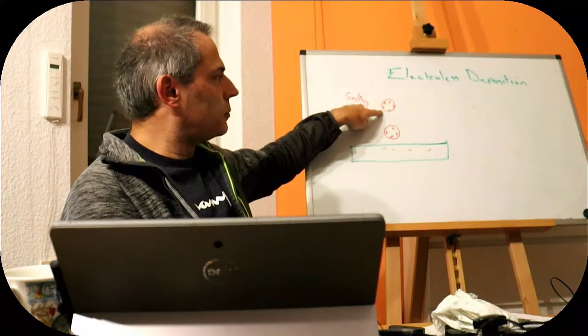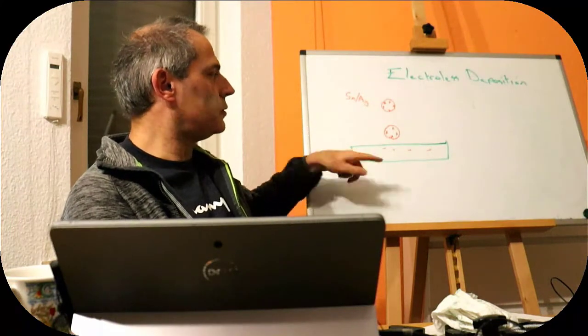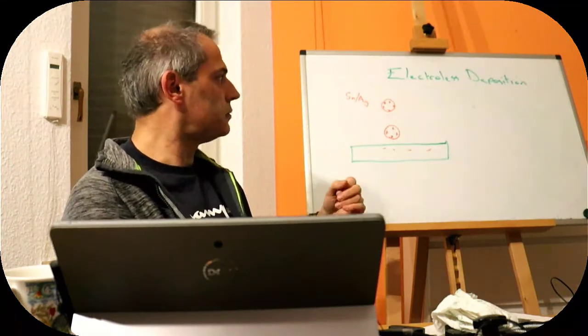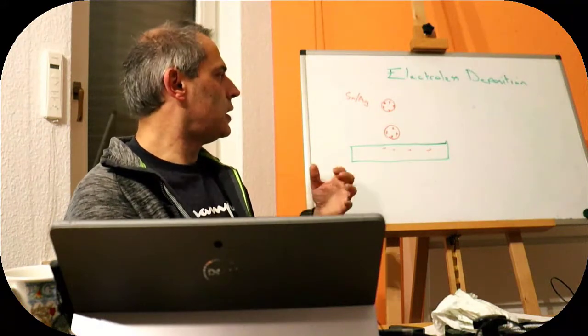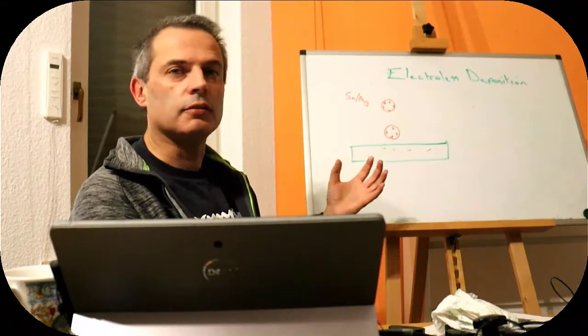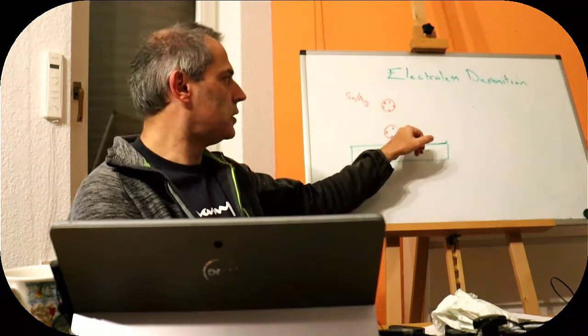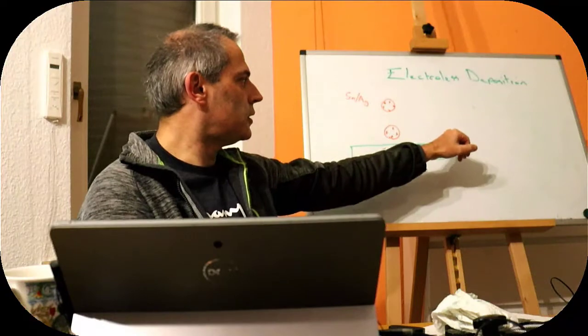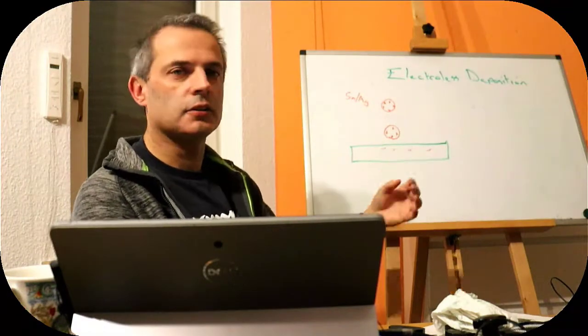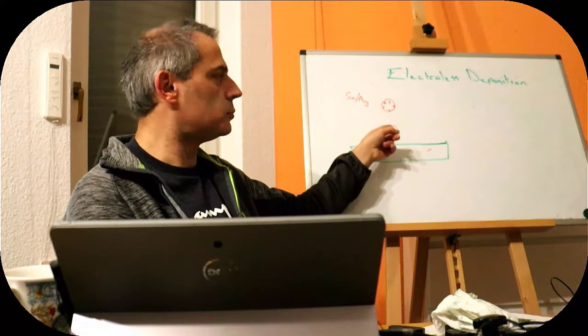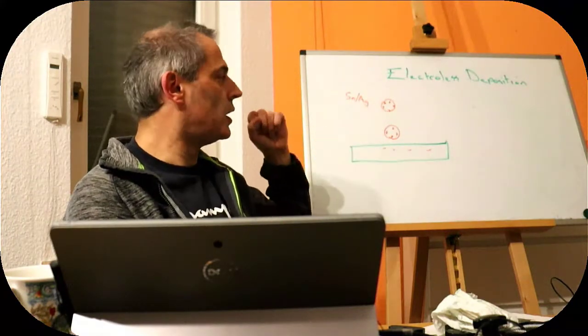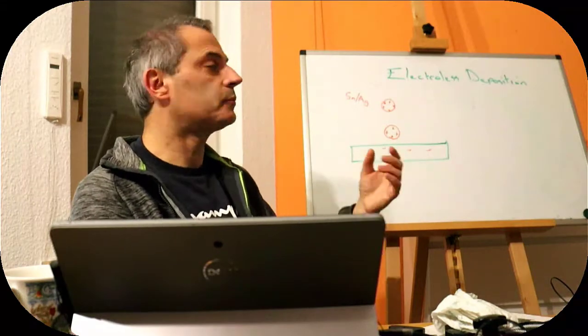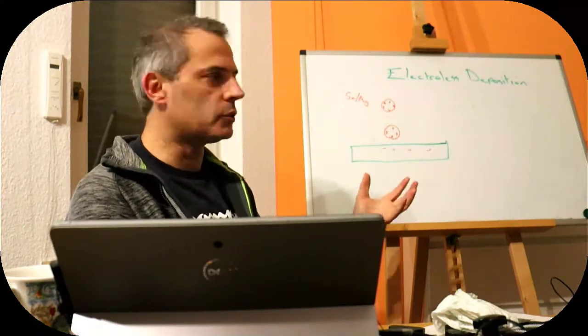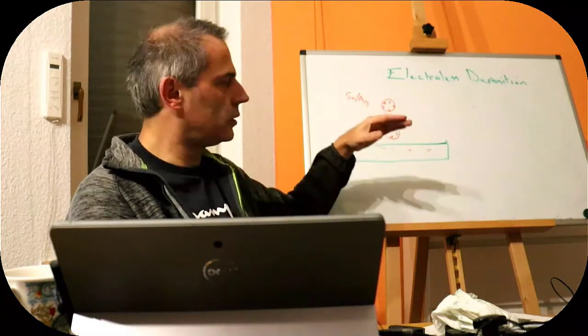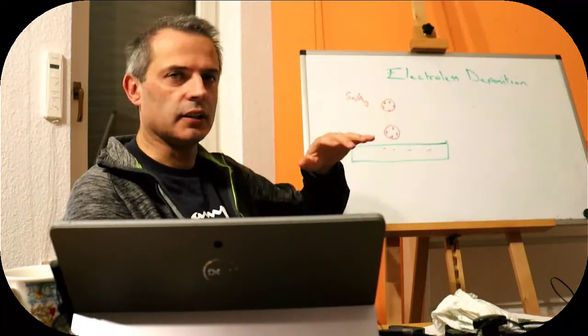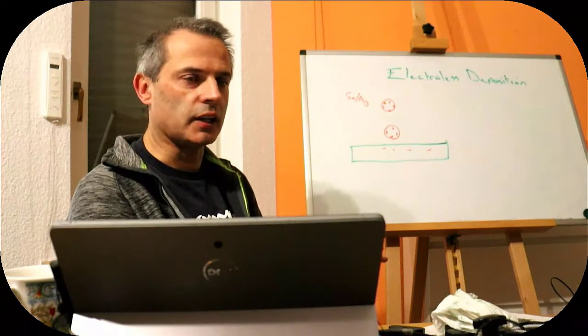If we take our positively charged colloidal particle and interact it with our negatively charged glass surface, they will approach each other, but they can't actually touch because both of these surfaces are hydrated. There's a water layer on the outside of the particle and there's a water layer on the surface of our glass. Likewise, if we have a surfactant in there to make this positive charge, that would also be in the way. It will be stuck on the surface of the particle, making it positive, but it would also be in the way and block the metal and the glass surface from interacting directly.